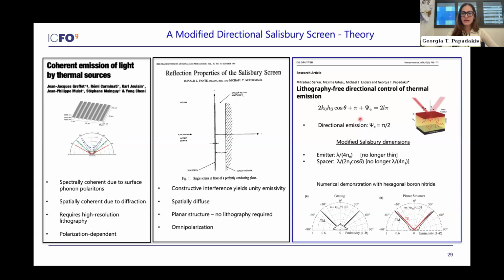And what we saw is that if we relax the standard conditions for a Salisbury screen that are described by this equation here that matches the phases of the incoming light with the light that comes out of interference in this dielectric spacer here, is that if we make the emitter a little bit thicker than this limit of ultra-thin emitter shown here, then you can actually generate very directional thermal beams.